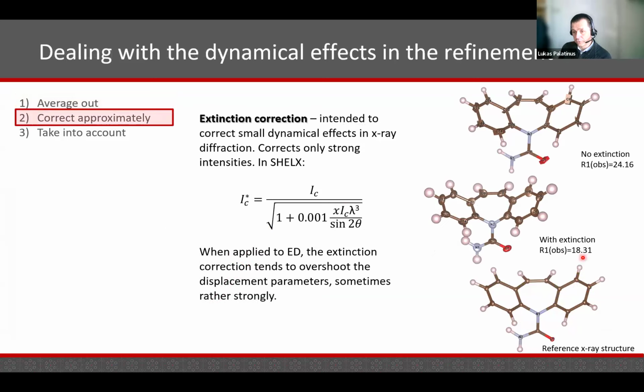The second and non-exclusive option, of course, we can use one on top of the other, is an approximate correction, which is known in X-ray diffraction or X-ray crystallography as extinction correction. Extinction correction is a simple correction for small dynamical effects used in X-ray diffraction, and therefore it's also an obvious thing to try for electron diffraction. And indeed, sometimes it helps quite significantly. For example, in this refinement of the molecule of carbamazepine, which gives an R factor of 24% when extinction is not applied and only kinematical approximation is used. And with extinction applied, we obtain a significant improvement of the R factor from 24 to 18.